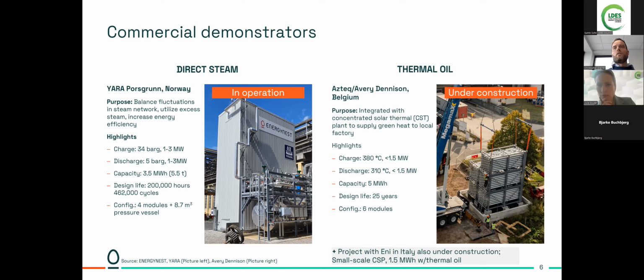On the right side, you see the project we have for concentrated solar thermal. Here our battery is integrated with a solar field in a plant which is under construction in Belgium. This solar field operates with thermal oil, and we charge the battery with hot thermal oil up to 380 degrees. And we discharge thermal oil back to a heat exchanger, which provides a different thermal oil to a nearby factory owned by Avery Dennison. So the battery here has a capacity of 5 megawatt hours and a charge and discharge capacity up to 1.5 megawatt. And also here the design life is 25 years.